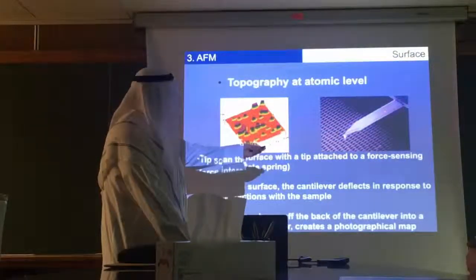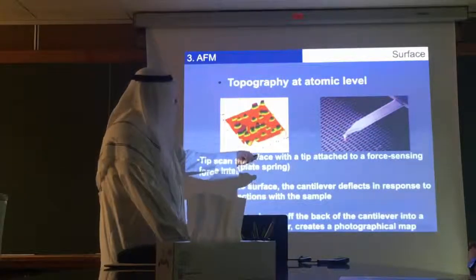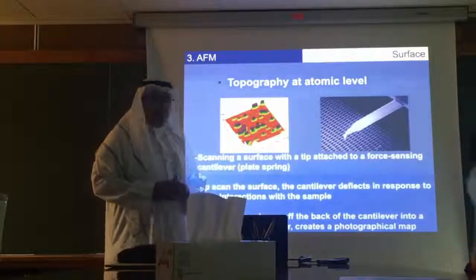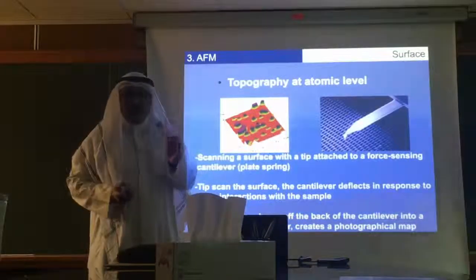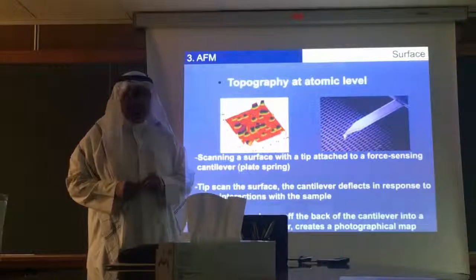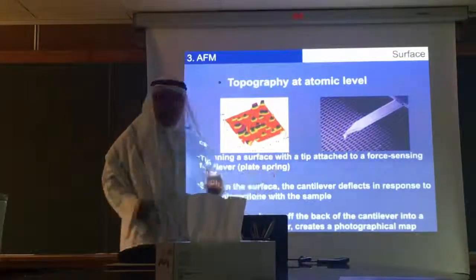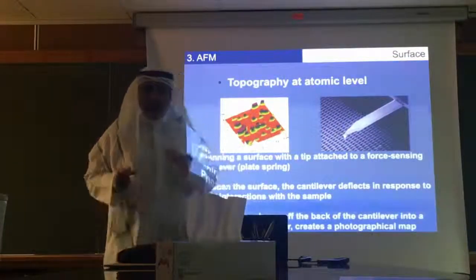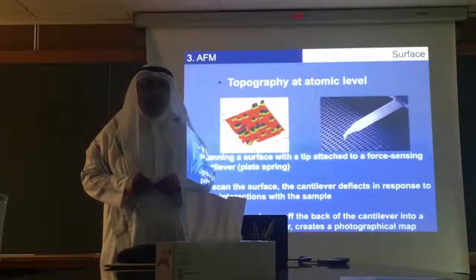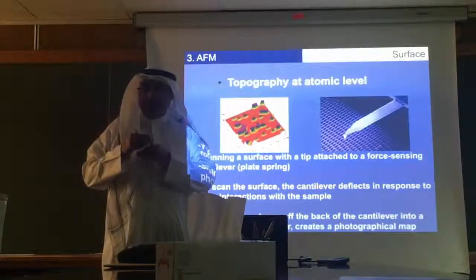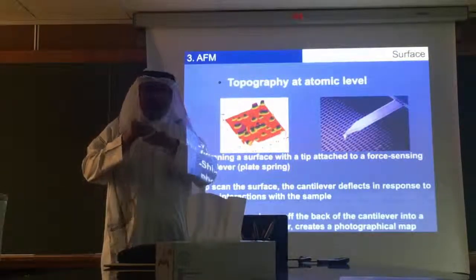This is the cantilever that I told you about, and this is the sharp tip. And you can change the tip. You can make it sharper if you have very small particles. You can make it wider if you have larger particles. And you can do more with this technique. Unfortunately, we don't have this at Kuwait University, but you can study the magnetic properties and the interaction between the surfaces.